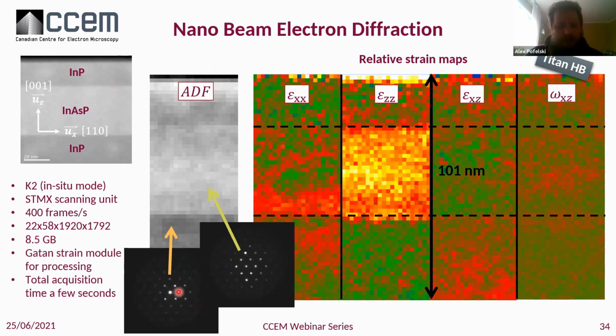And here you have two examples of those diffraction patterns. In the indium arsenic phosphide, you can see that the intensity distribution is not uniform. So it might be questioned whether the center of mass is really the best approach to find the position of those disks. We'll definitely have to try the Py4DSTEM module to see how this goes. But these are the strain maps I obtained with this sample using their approach: epsilon xx, epsilon zz. It is supposed to be zero everywhere and just have a positive deformation in the indium arsenic phosphide layer. Kind of, but there is still a bit of noise. So this is to be explored. I really think this is coming from the center of mass approach, and that this noise contribution could be improved.